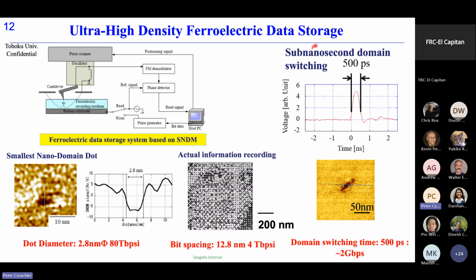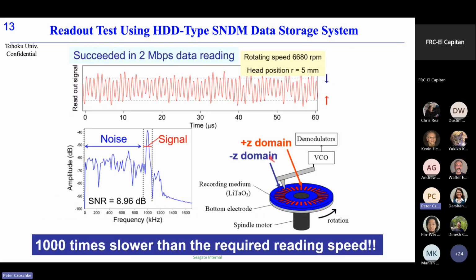And also, we confirmed the very fast switching characteristic. In this case, we applied a 500 picosecond voltage burst to the medium, and we succeeded in reversing the polarization. This means that, in principle, the writing is possible, but in this case, we have to use a very thin material. But also, the data storage has a problem. It's the reading speed.